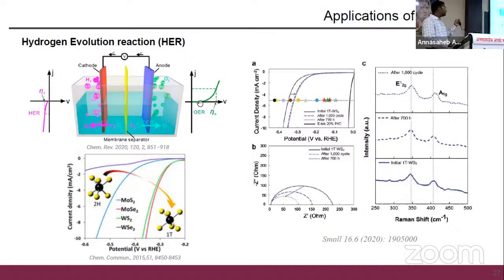From that calculation, you can find out how much hydrogen you are evolving in these materials. You can also do some Nyquist plot or impedance spectroscopy to find what other things are restricting these materials. As your material shows better performance, the Nyquist plot will show a smaller radius for this semicircle.